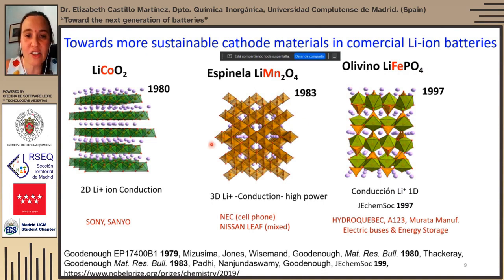And this crystal structure has three-dimensional tunnels for lithium-ion diffusion. This higher dimensionality with respect to the layered oxides gives this material higher power and allows it to be used for applications where higher power is required.